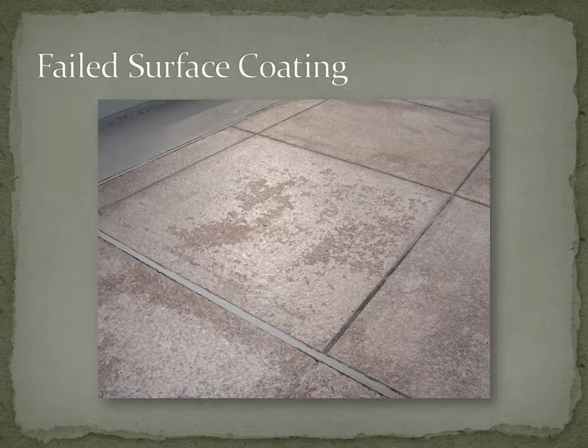And you'll make it to the bank, and the check will clear, and you'll be looking good for nine months or maybe even a year. But then it's going to start to flake. It's going to delaminate, and you're going to have certain areas where it comes off completely. And in the areas where it doesn't come off and just delaminates, it's going to completely wash out the color of the stone. You'll have this plastic type of look. And with quartzite and granite and other stones, it'll cause the stone to start spalling, because the stone will not be able to breathe the way it's supposed to breathe.